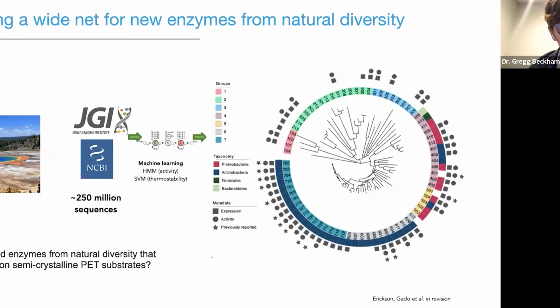And so we were interested, and this is in collaboration with John McGeehan at the University of Portsmouth and other colleagues, in understanding, can we find enzymes from natural diversity that not only were thermophilic and can operate around 65 to 70 degrees C, so right around the glass transition temperature of PET, where enzymes have been found to be most efficient, but also can we find enzymes that are active on crystalline or semi-crystalline PET substrates? And so this is work from Erica Erickson and Jafet Gado. This is in revision now, and I hope that it will be accepted very soon.